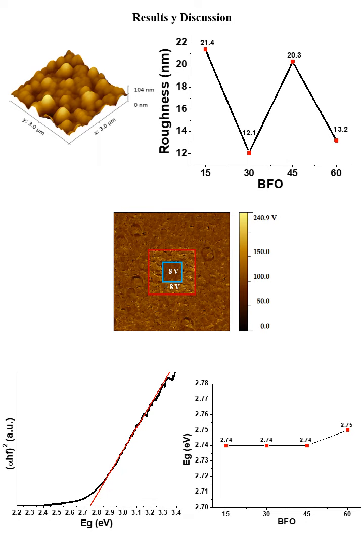Lastly, the optical behavior was evaluated through the reflectance and transmittance spectra, and it can be seen that the optical bandgap is changed slightly with sintering times, where the values obtained were around 2.74 electron volts all the way to 2.75 electron volts.